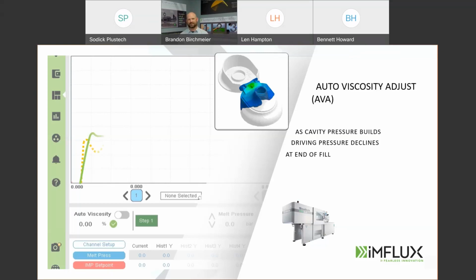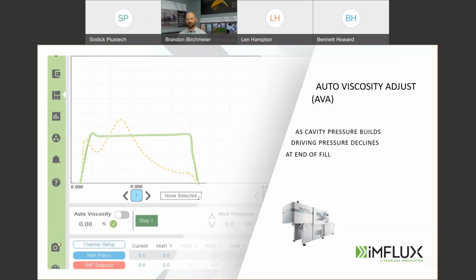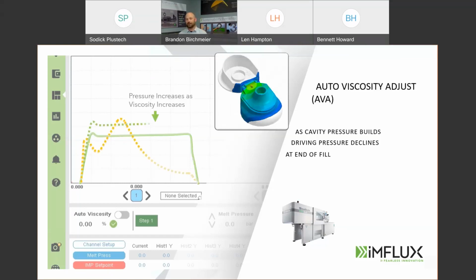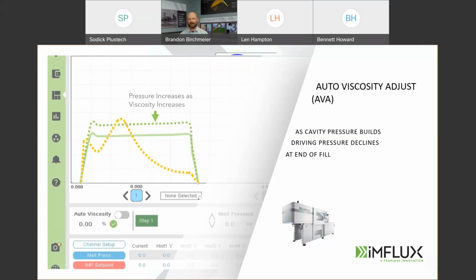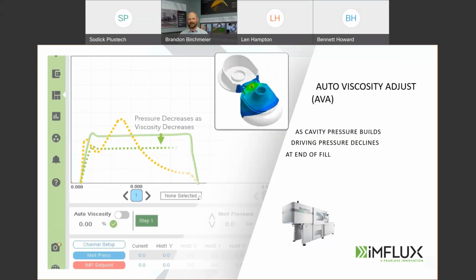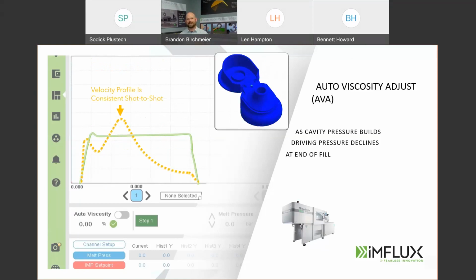So how does this work? So we'll go back to our cap that we had, the toothpaste cap. And the way this works is, right, we'll set up our initial process that we're happy with. However, as viscosity changes, you can see what we'll do is we'll recognize the change in viscosity of the material and automatically adapt the driving pressure. But what remains the same is that velocity profile. So I can modulate the pressure up and down to maintain that constant velocity profile. And this shape is important. This shape's dictated by the geometry of the part. I'm not telling the machine what the shape should look like, the velocity. That's literally dictated by the part in the mold. It finds how it wants to fill, and then we'll just modulate the pressure in real time based on the material.